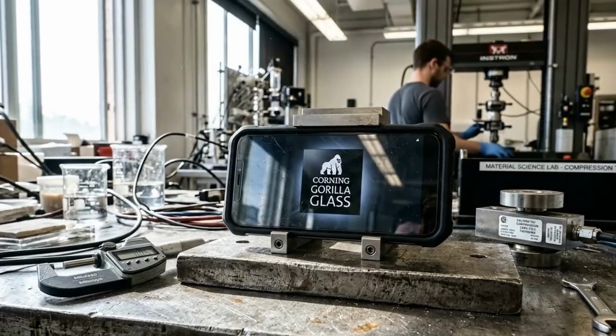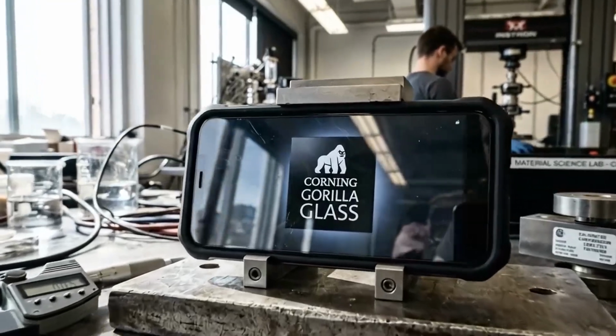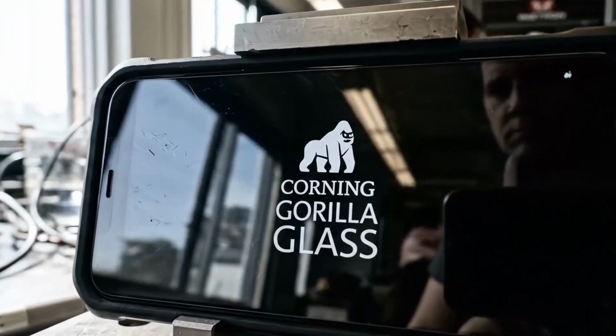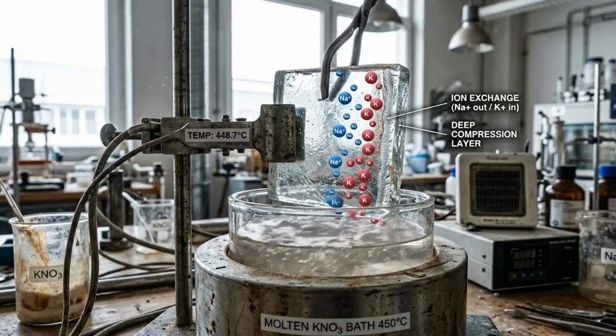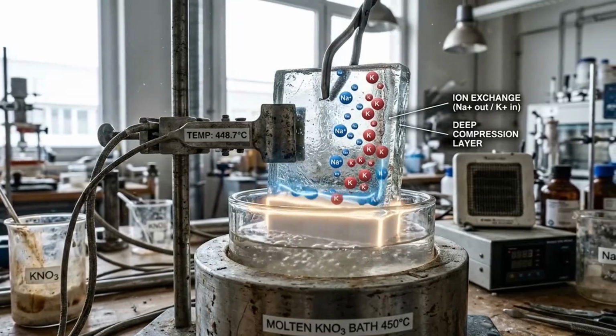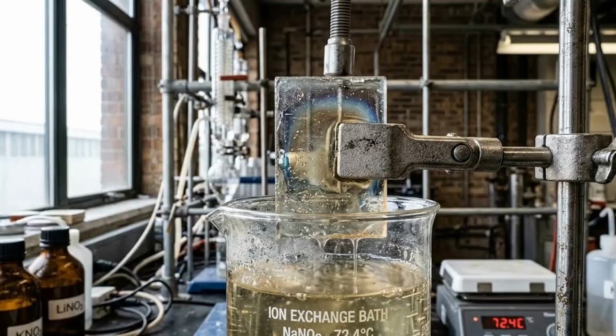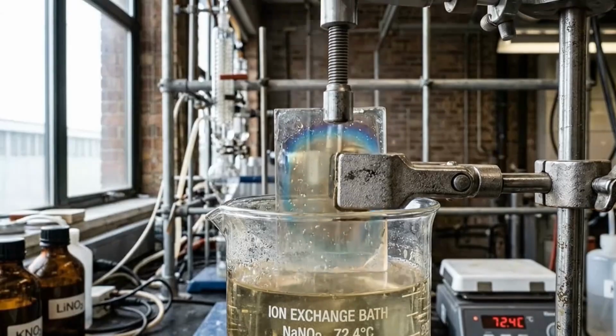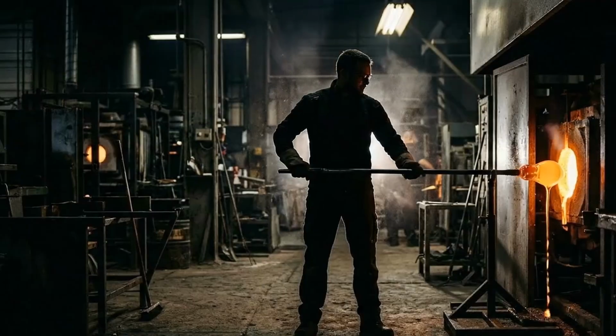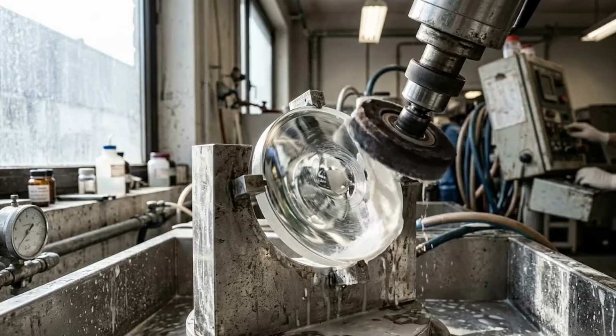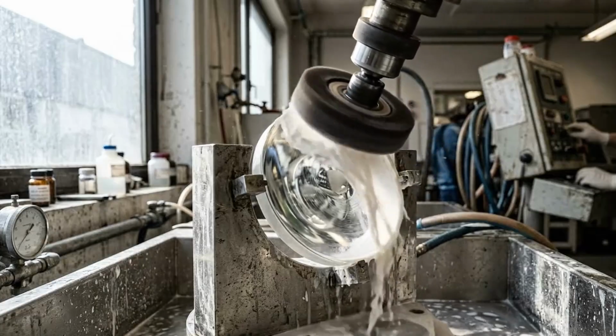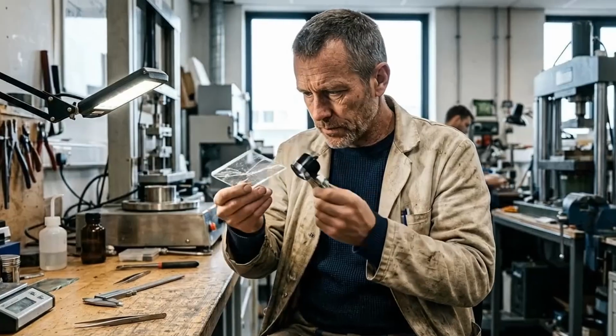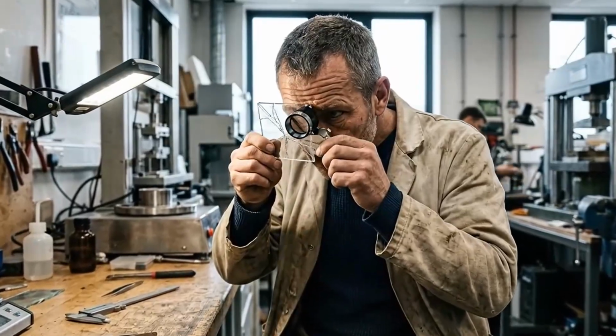Modern versions of this principle are used in Gorilla Glass and other chemically strengthened glasses for phones. Potassium ions are exchanged for sodium ions on the surface, creating compressive stress up to 10 times deeper than thermal tempering. So glass isn't just sand. It's a carefully engineered material where chemistry, cooling rates, and surface treatments decide whether it's fragile or incredibly tough.